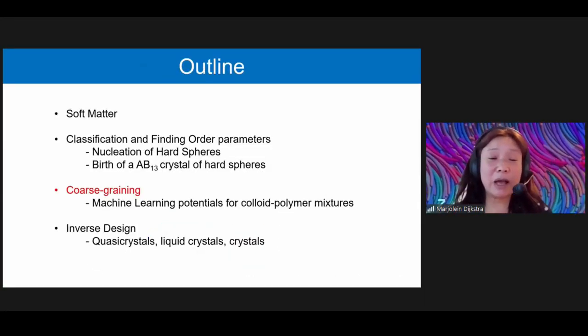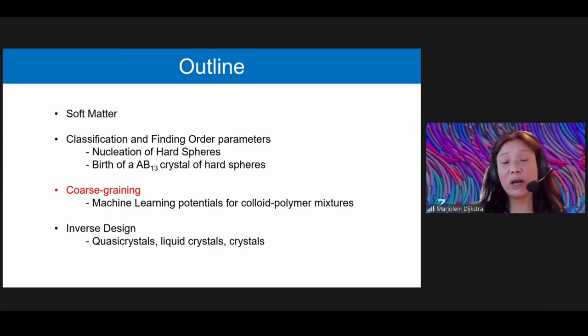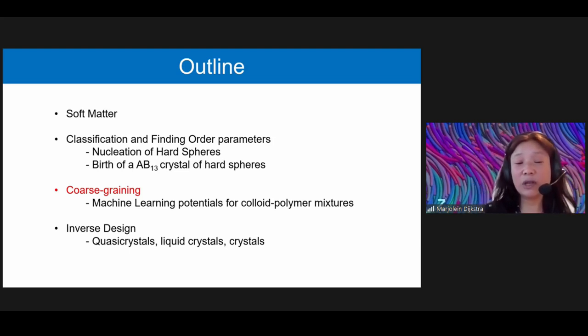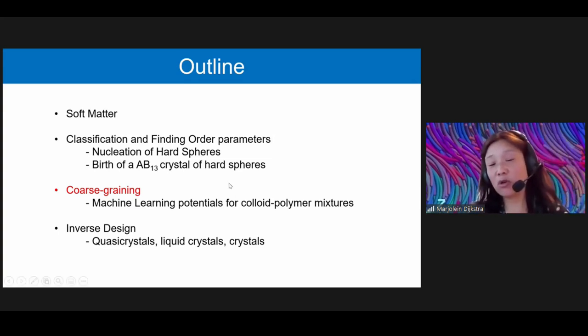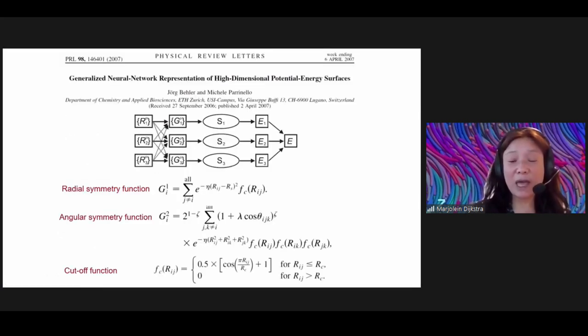So we can use machine learning to find what the relevant order parameters are. We can train a neural network to study the nucleation of several systems, but we can also use machine learning to coarse grain systems. And so often in colloidal suspensions, you add non-adsorbing polymer or you add salts to the suspension in order to tune the effective interactions. And so we went back to the good old colloid polymer mixture, where by just adding a non-adsorbing polymer, you can induce depletion interactions between the colloidal particles.